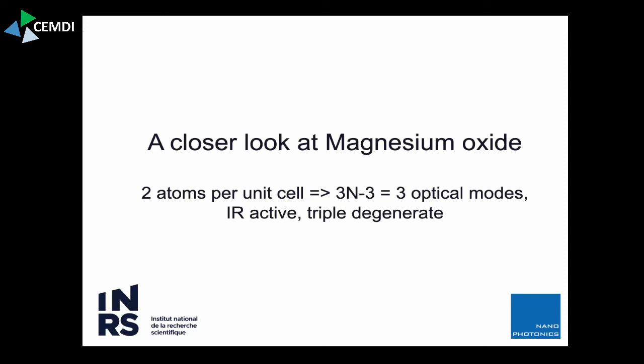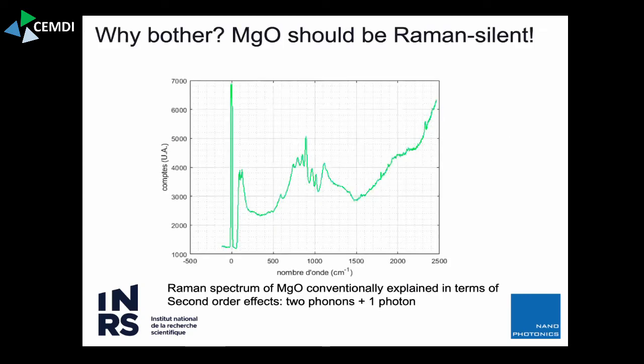And magnesium oxide is a fantastic material. It's chemically stable. It doesn't dissolve in water. It forgives you if you shine full power laser light on it. So it's almost ideal. It's Raman silent. It's only infrared active. It corresponds very much to the chain that I showed you in the first place. It's AB, AB, AB in all directions.